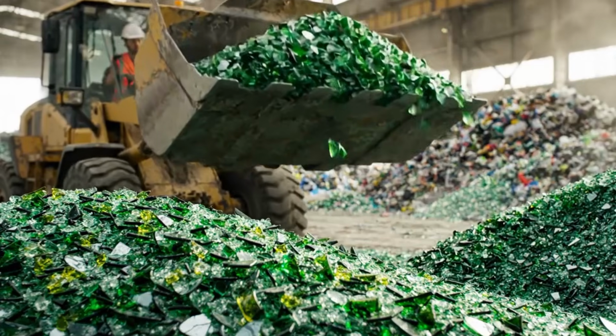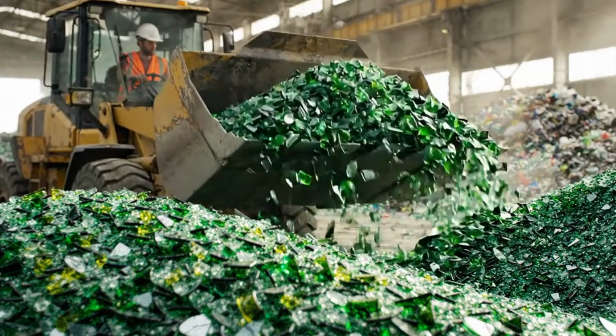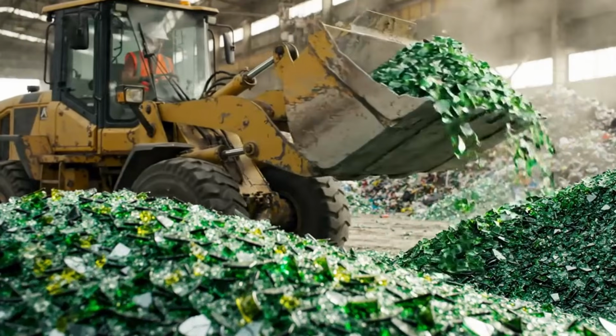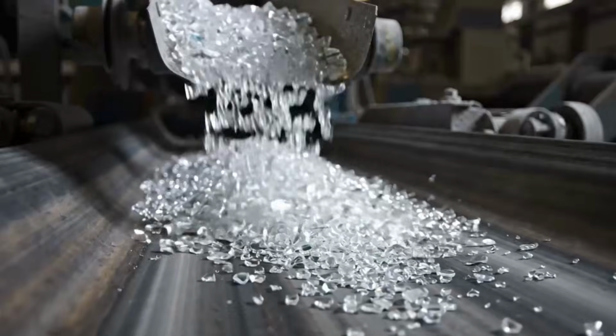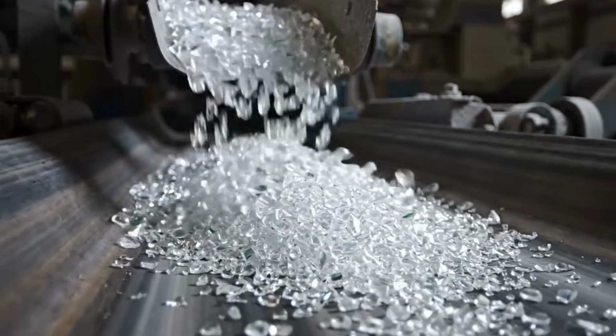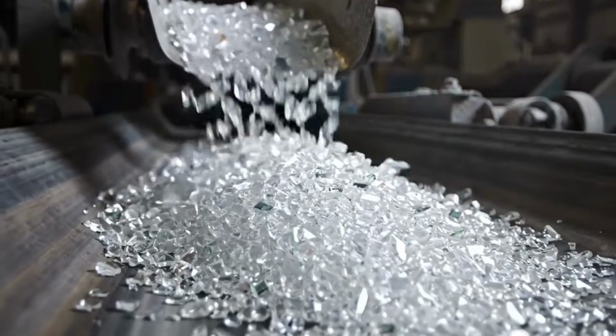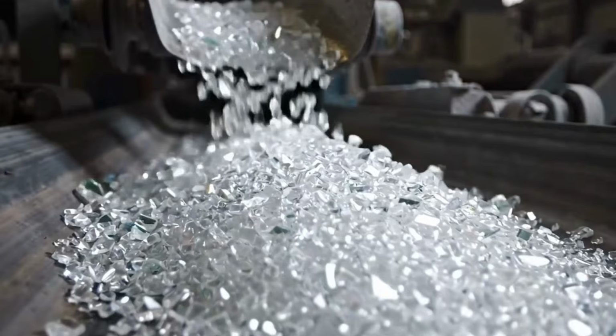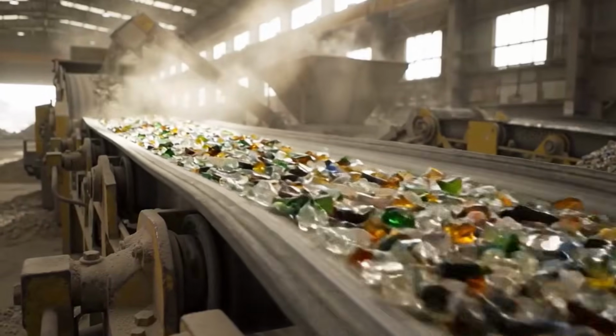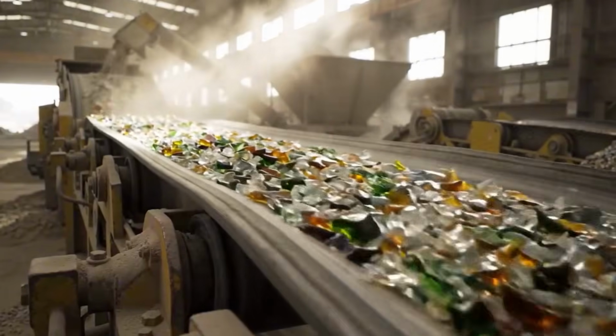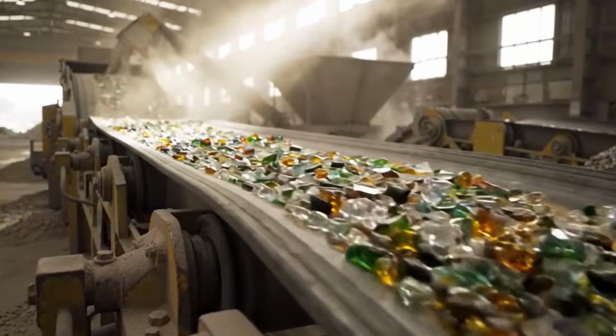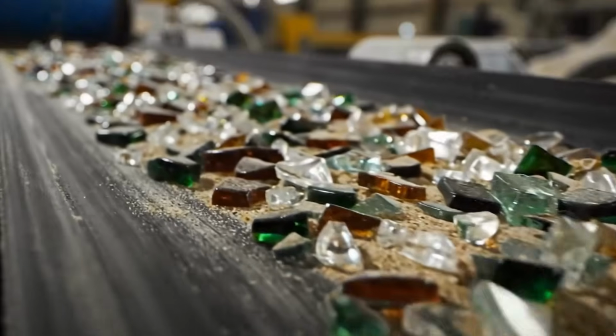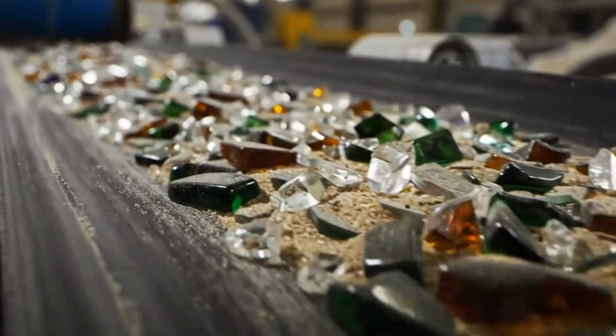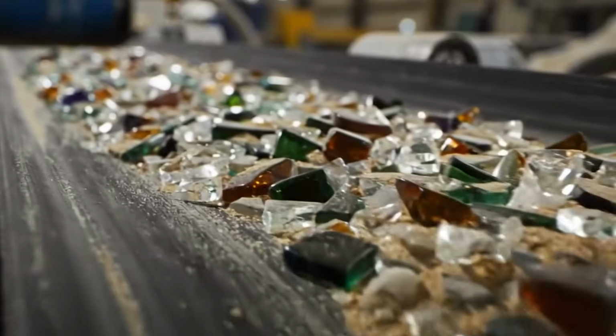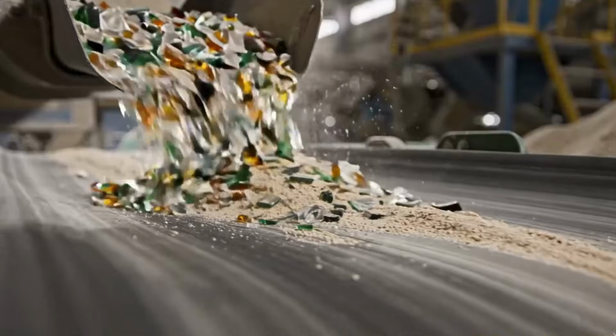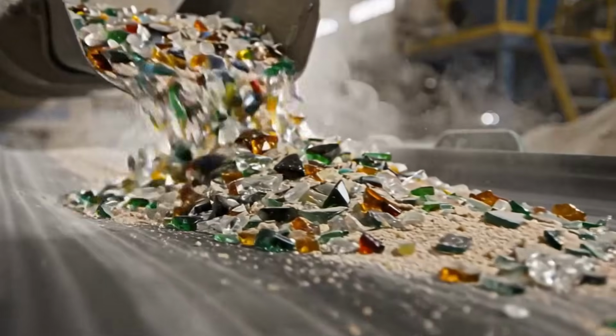The most important part, though, is still the cullet, which can make up anywhere from 20 to 70% of the batch, allowing the melt to flow faster and cutting energy use by up to 40% compared to brand new raw materials. Adding just 10% more cullet can reduce energy consumption by about 3% and significantly cut CO2 emissions. With the predetermined formulas from the factories, the mixture is mixed evenly and ready for the melting process.